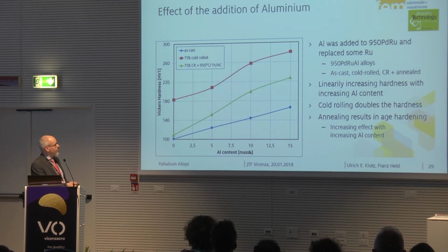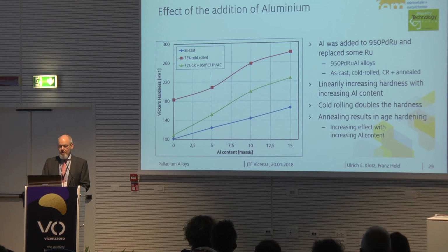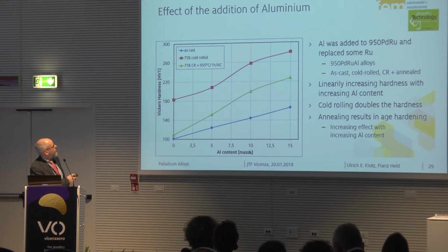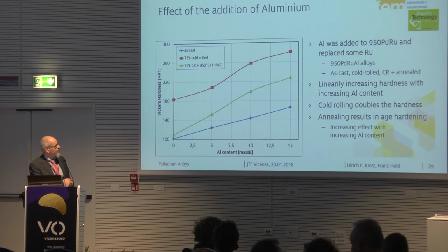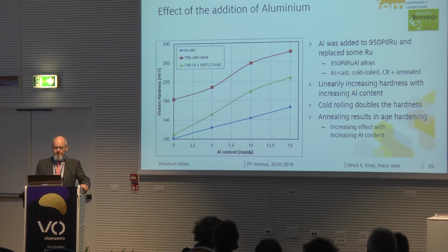We also tested aluminum, and we see the blue curve here, the effect of aluminum content on the hardness. We get a linear trend up to 15%. We get also in the right range of hardness, and we see that these alloys show a certain age hardening. So we cold rolled the material, then we get a strong increase, and then we annealed it at a certain temperature, and we get a certain difference, and you see that the difference increases with increasing aluminum content. So this is also an interesting result.